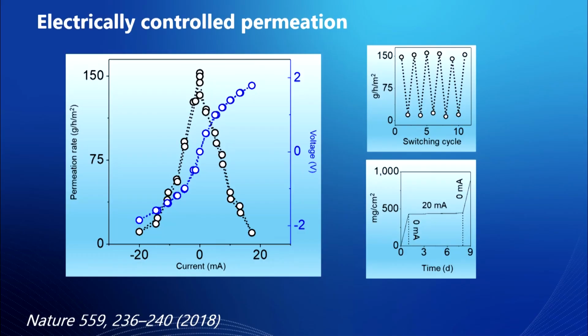By passing a current, the water flux through the membrane can be controlled from on state to off state, or even precisely controlled in between. For example, you see that it can switch on and off multiple times by applying a current. Water either goes through or gets stopped, or you can switch off the membrane for a longer time by applying a current through the membrane. So that's a concept for a smart membrane, but this is definitely at low TRL. This is a proof of concept experiment we did several years back.